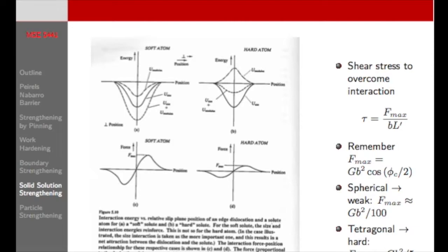Okay, so we have to combine these together. So here's our attraction. Our size effect is always negative. Our modulus effect can either be negative or positive depending on the stiffness of our substitutional atom.